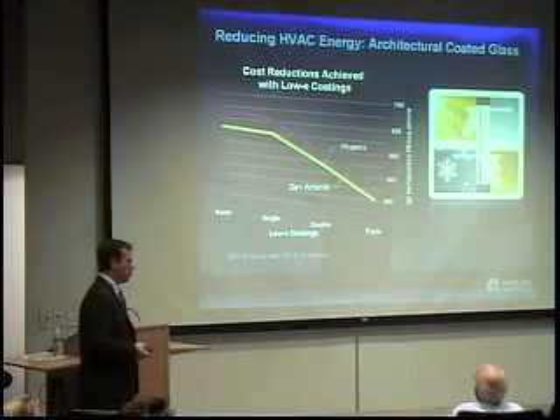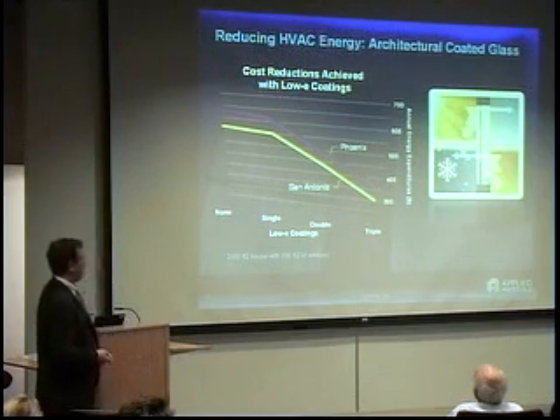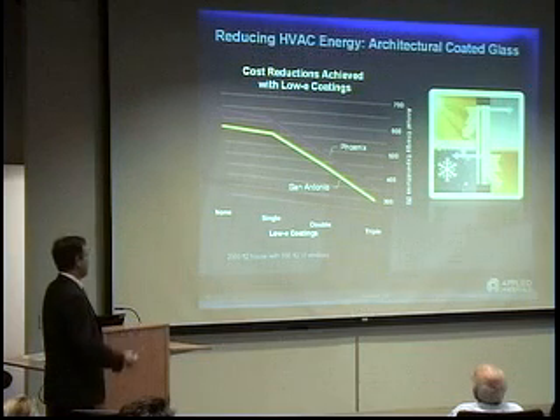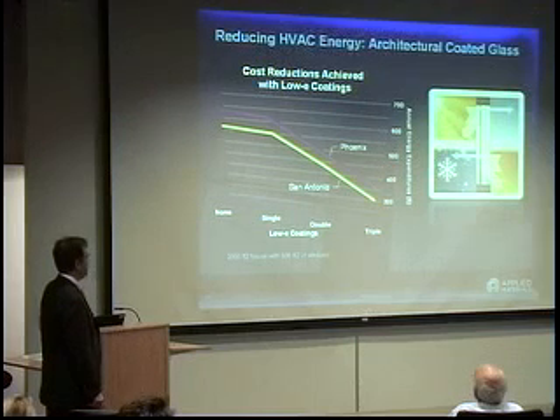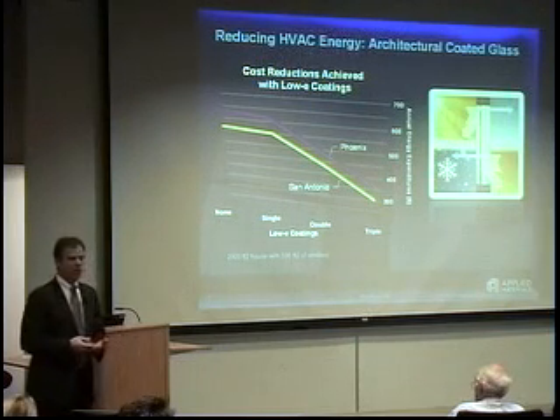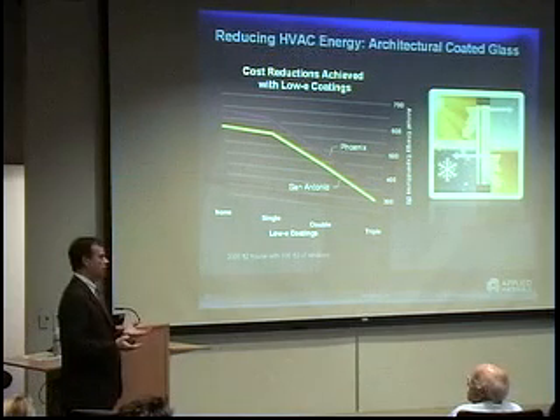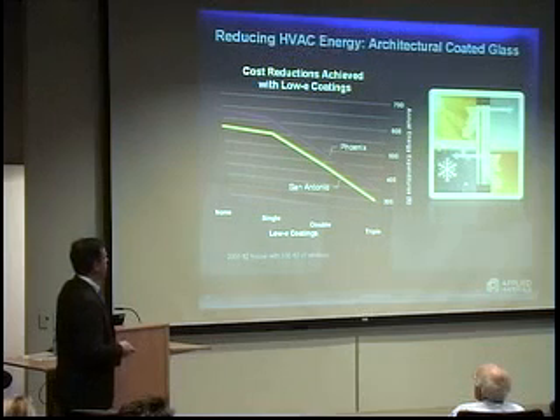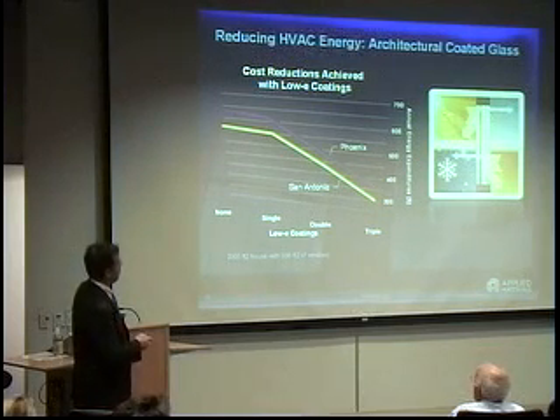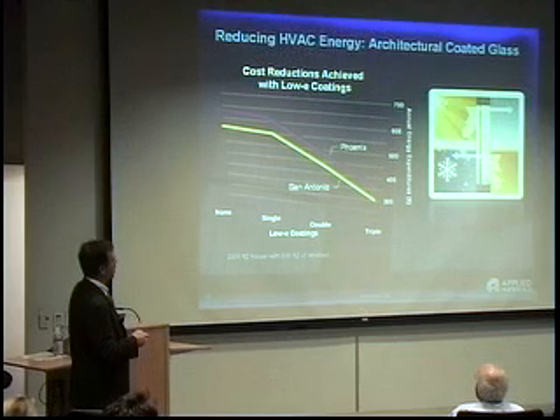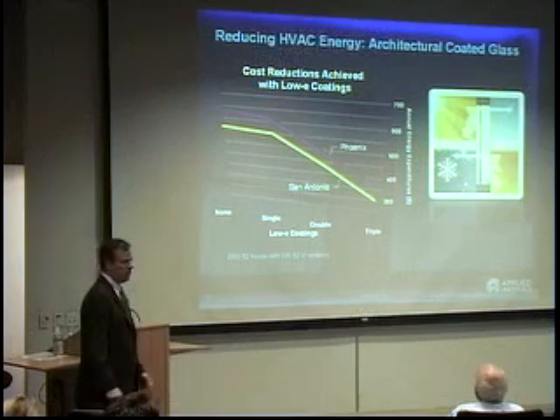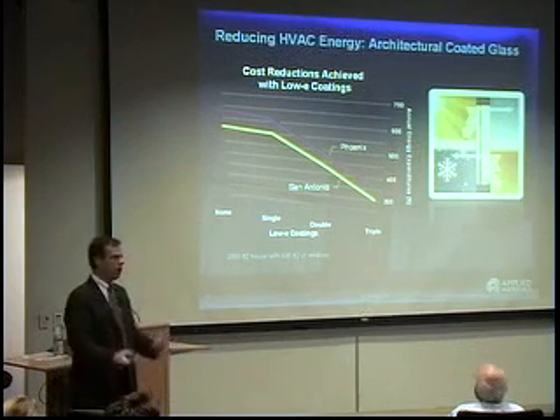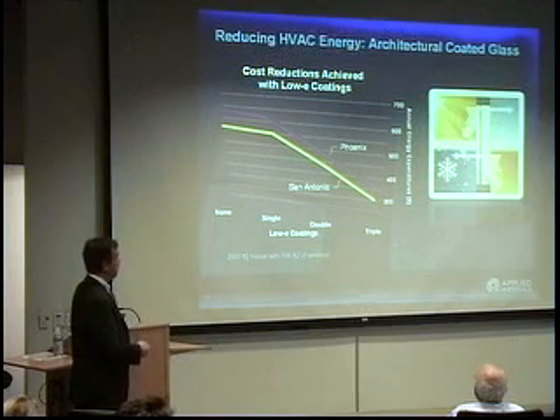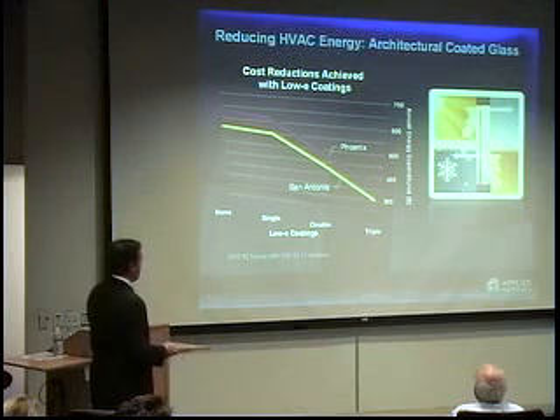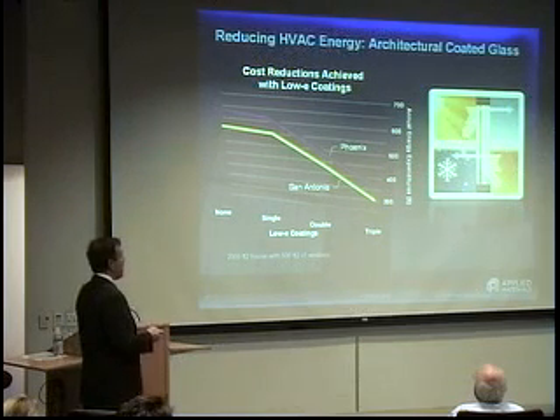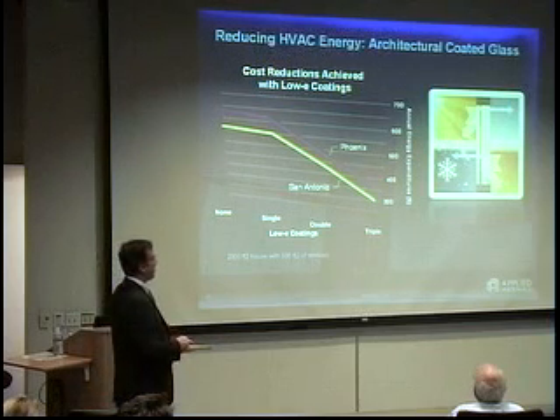So first, an example of what we can do with the air conditioning and heating. This is something that's been developed, really made commercial, over the last maybe 10, 15 years. It's called low emissivity coated glass. We take a standard glass and we coat it with a metal oxide set of films. And basically we try and keep, if you look at this from the outside and this is the inside, and it's a hot day, you try and keep the IR heat out and let the visible light in. So you get the benefit of the window, you get the natural light in, but you try and keep the heat out. You might also try and keep the UV out to stop damaging furniture or paintings or what have you, if you really want to get fancy with this kind of technology. And the other way works too, if it's in the winter, to try and keep the heat in.